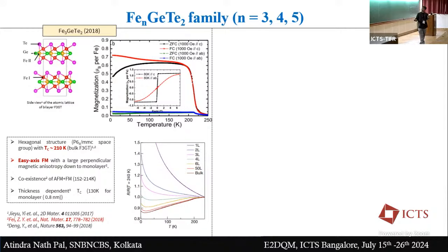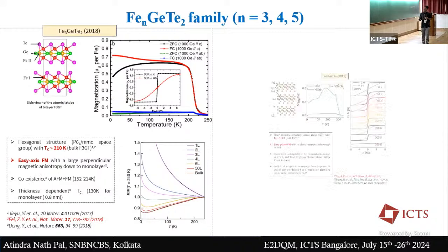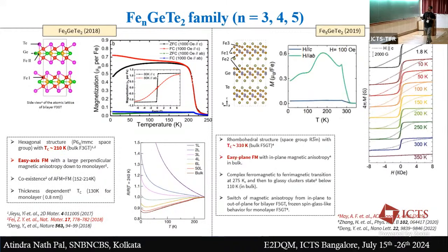Okay, and people have observed the coexistence of antiferromagnetic and ferromagnetic order in this kind of system in the 150 to 214 Kelvin range. This is more extensively studied than the other two sister compounds. Okay, and if you go to F5GT, you can already see the magnetism behaves very differently.